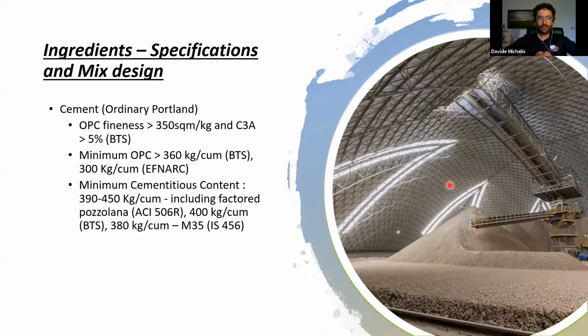Cement. Of course, cement. Not all cements are proper for use with a shotcrete mix design. We have to think about what kind of mix design. For example, we need a pretty high fineness of the cement, 350 square meters per kilo, and we need a minimum amount of OPC of 360 kilograms per cubic meter when we start to design our mix.